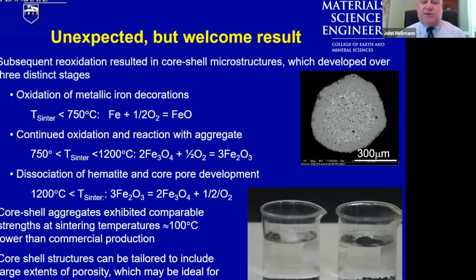This was borne out in subsequent studies, and it allowed us to manufacture proppants with what we term the core shell microstructure, where we take a ceramic particle or proppant, sinter it to full density, and then de-densify it while maintaining a dense outer shell. This yields a hermetic particle with controlled specific gravity to the point where you can make a neutrally buoyant ceramic proppant, a proppant that floats in water, which has significant environmental benefits as well as economic benefits, because most hydrofracturing liquids are laced with different chemical species to promote the suspension of the proppant particles in the hydrofracturing fluid during the injection process. A neutrally buoyant particle will require fewer of those chemicals, a significant environmental impact improvement.